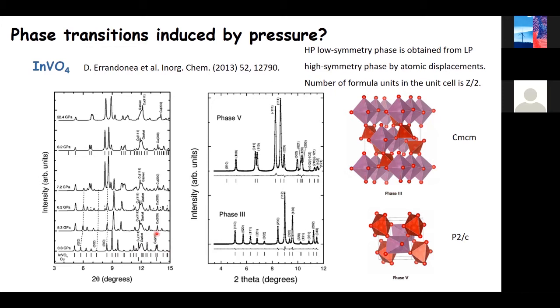This happened again when we started increasing pressure, at 5.3 GPa. Still, we have only the orthorhombic low pressure structure. However, when we increase the pressure further, we reach 6.2 GPa, and you start seeing some new peaks, which I depict by asterisks, like this one, this other, and several more, which are an indication of the onset of the phase transition. As we keep increasing pressure, you can see that the peaks from the low pressure phase start losing intensity. This is clear here. And these new peaks start growing in intensity. If you increase the pressure further, you lose the peaks of the low pressure phase and you get all new peaks, which correspond to the high pressure phase.